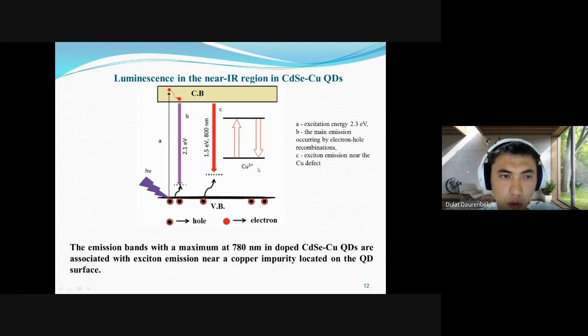Defects. As you know, quantum dots are very small, about 2 to 10 nanometers. That's why it's very difficult for impurities to go inside the quantum dots, because their surface states are more powerful in this case. All impurities try to catch on the surface area, and they are not always incorporated in the lattice of the quantum dots. Usually they are like defects. That's why the defects influence the main energy transfer by decreasing the energy like this.